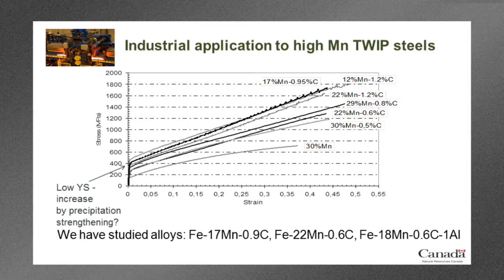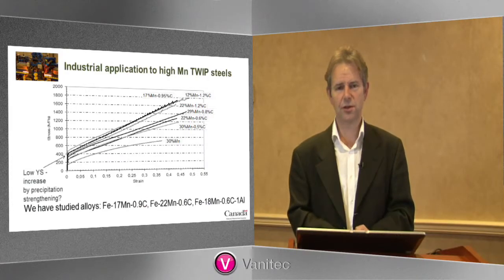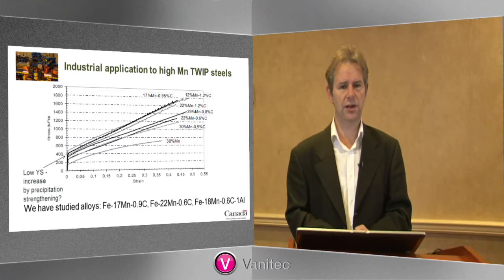There's a wide range of possibilities, and the one which shows the highest strain hardening was the 17% manganese, 0.9 carbon steel. What I would point out to you is that although these steels are fully austenitic and they have a very high ultimate tensile strength, they do have a very low yield strength. And if you're looking at applications for automotive, for chassis, body in white, safety related applications, crash applications, then you really do need to have a higher yield strength. Probably the minimum would be 700-800 megapascals that you want for most of these applications. So we need to find some way of strengthening these steels if we want to use them directly in the body in white.